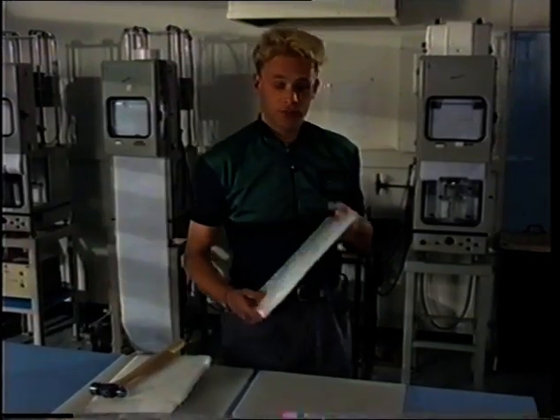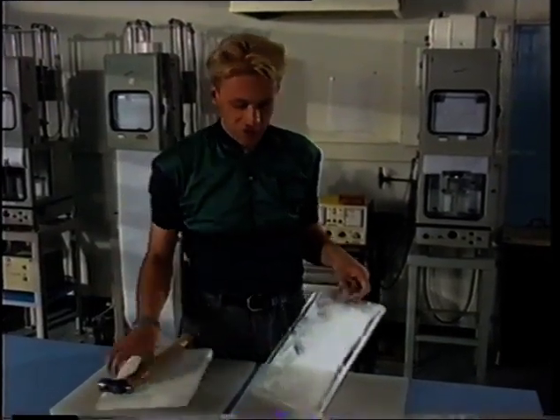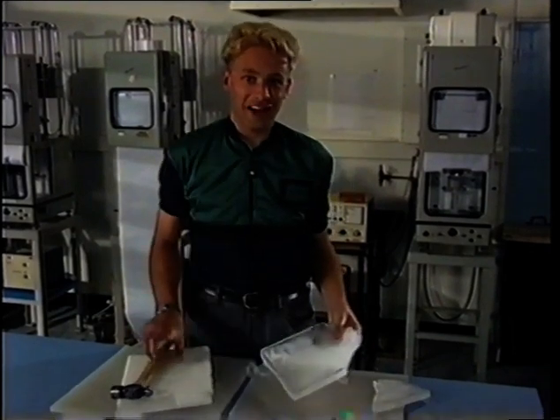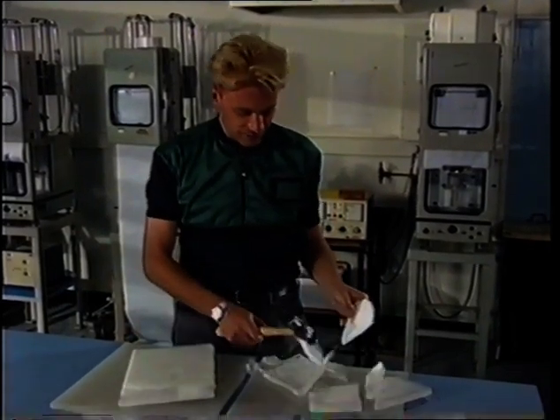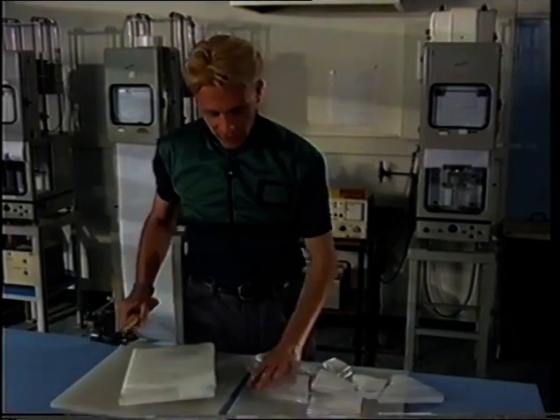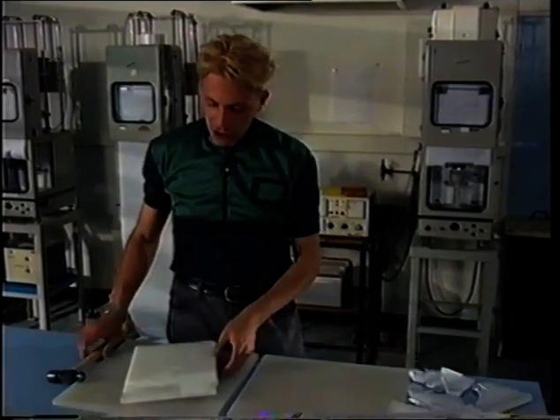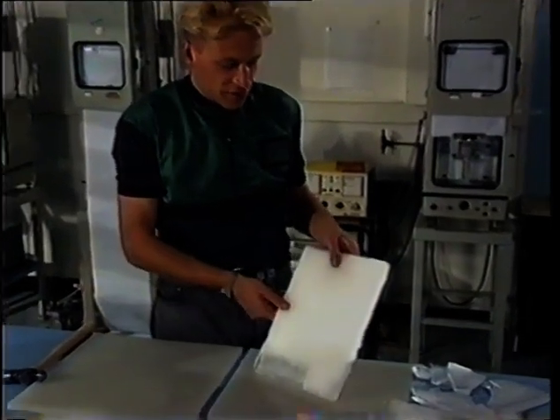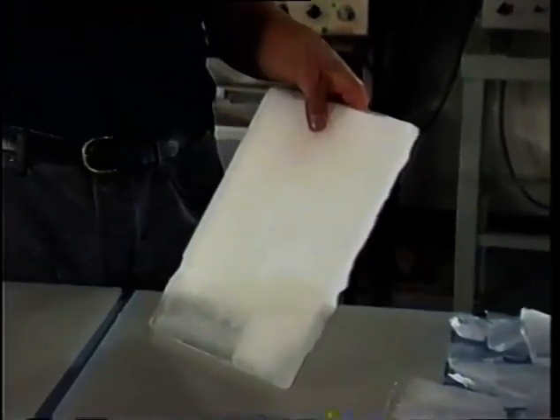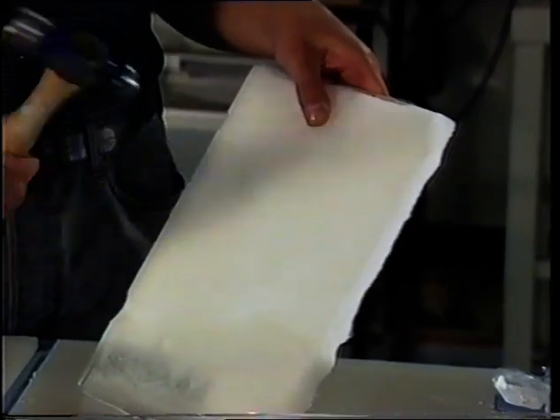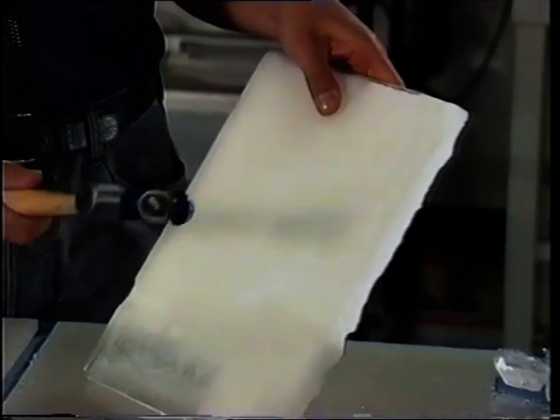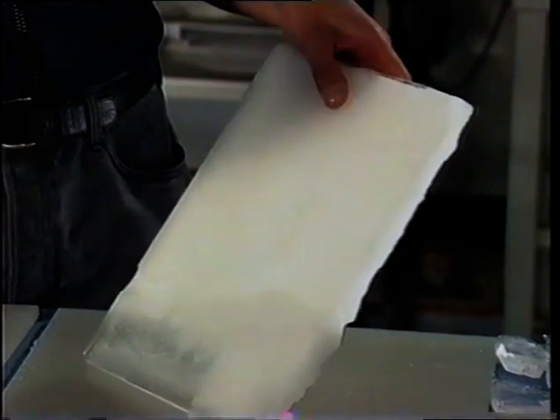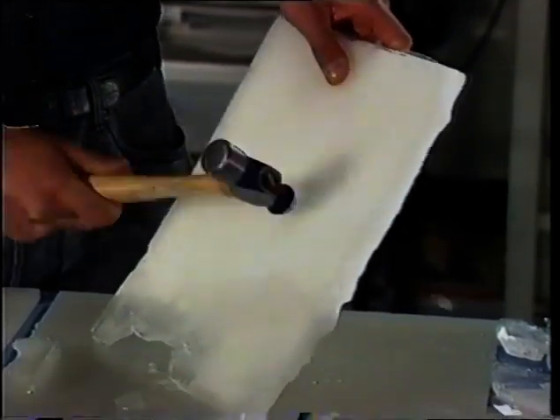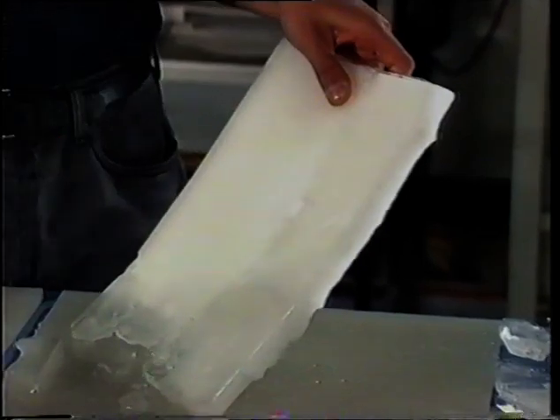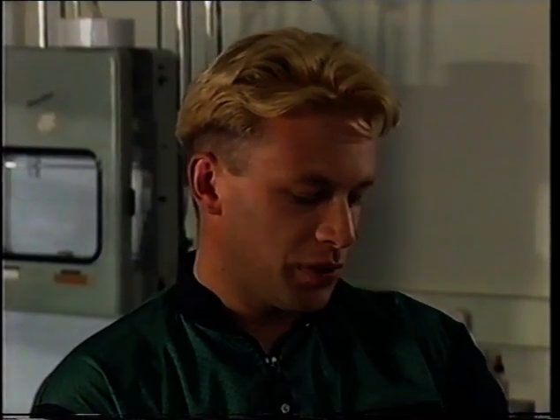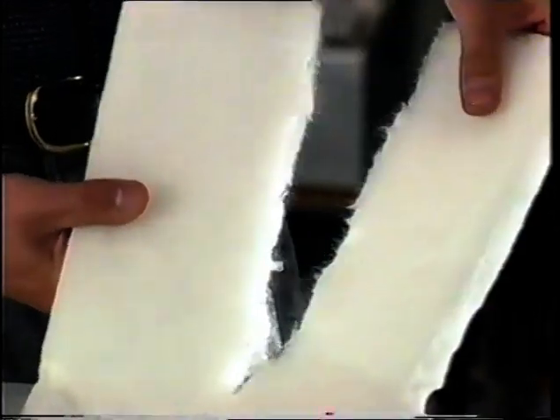This is ice, and when it breaks, it does so instantaneously and quite catastrophically. I'll show you that again with this hammer. This, on the other hand, is some ice with fibres embedded in it. And in this case, there's cotton wool embedded in the ice. And if I strike this with about the same amount of force using the hammer, you can see that it's much stronger. And in fact, it requires quite a hefty knock to get it to break. Now, if I gently pull the two pieces apart, you can see the fibres in between.